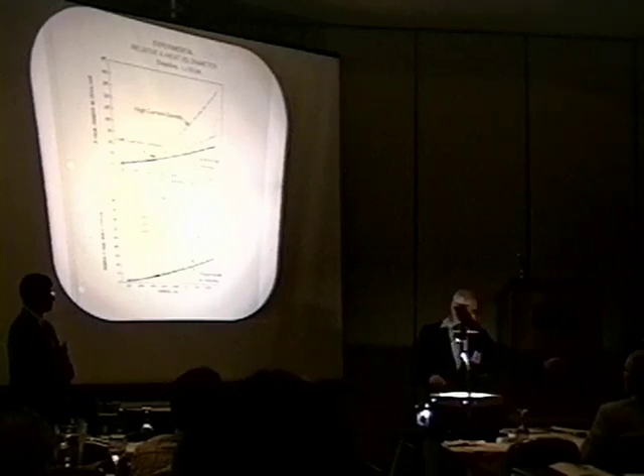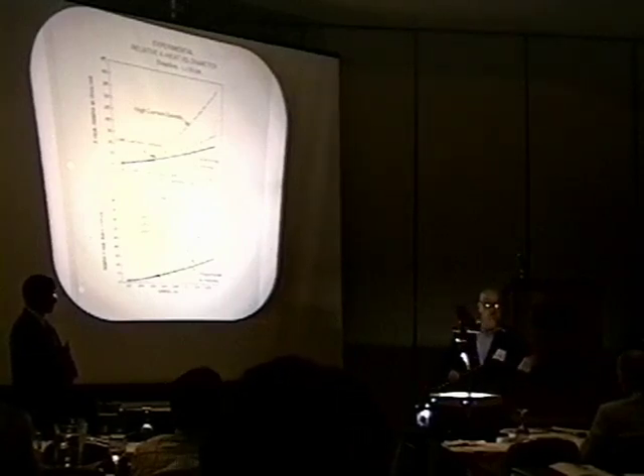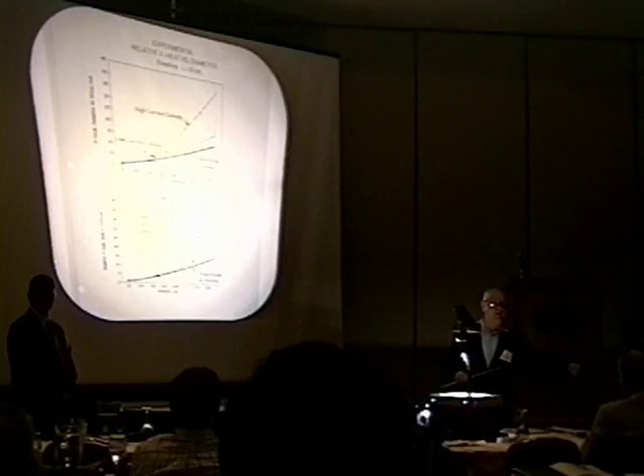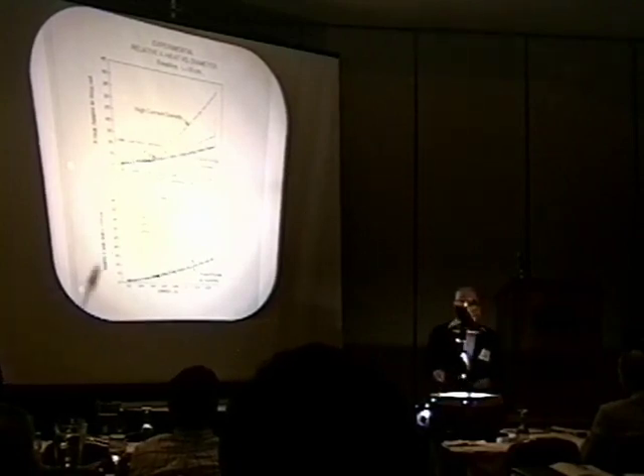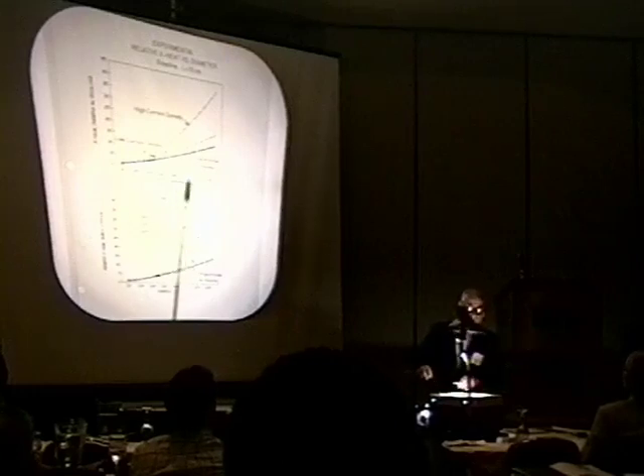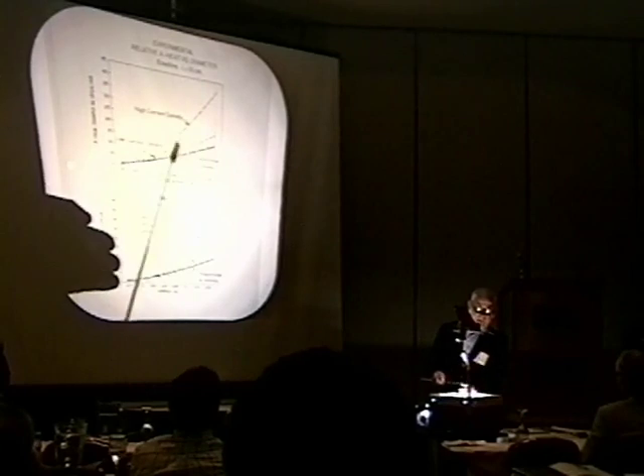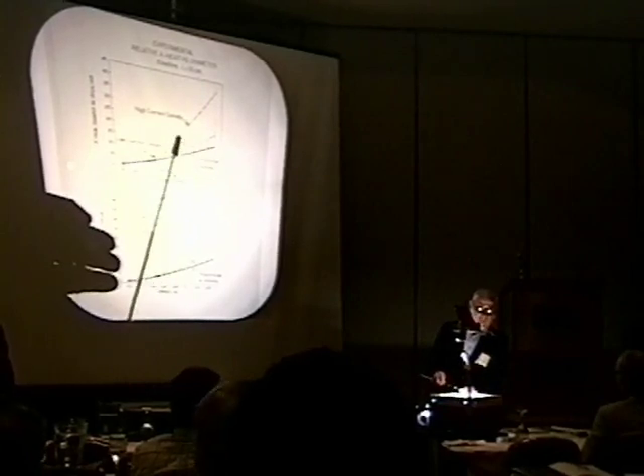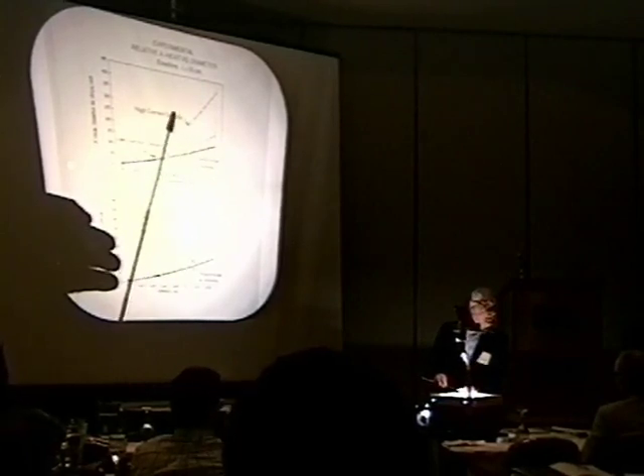Now, I talked earlier about active volume. Active volume is the volume where you're getting excess heat made. This says that in this case, the excess heat is being made through the bulk, except it's even better, even more than the bulk, and we'll talk about that in a minute. Again, it's either a little bit more or a lot, depending on the high current density.